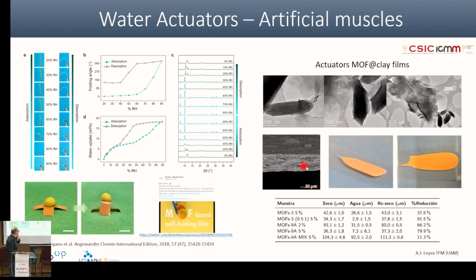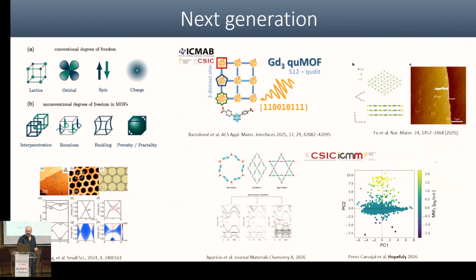So we deposit, we create these kinds of films, and they swell, they change the size by 91% nowadays. So I'm trying to measure that one, develop it, and trying to introduce mechanical movement plus absorption to see if it's contributive or is destructing my temperature exchange, but I think there are 2 contributions now, so it can be enhanced. And of course, it's moving up and down. So the easy thing that we didn't do yet is to put here some silver paste, let it go up, down, and close a system, okay? With the change of relative humidity.